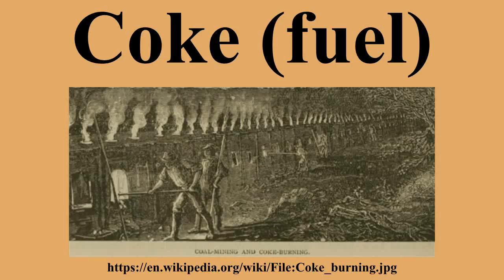It is generally considered that levels of 26-29% of volatile matter in the coal blend are good for coking purposes. Thus, different types of coal are proportionally blended to reach acceptable levels of volatility before the coking process begins. Coking coal is different from thermal coal, but it differs not by the coal-forming process. Coking coal has different macerals from thermal coal. The different macerals are related to source of material that compose the coal. However, the coke is of wildly varying strength and ash content and is generally considered unsellable except in some cases as a thermal product. As it has lost its volatile matter, it has lost the ability to be coked again.